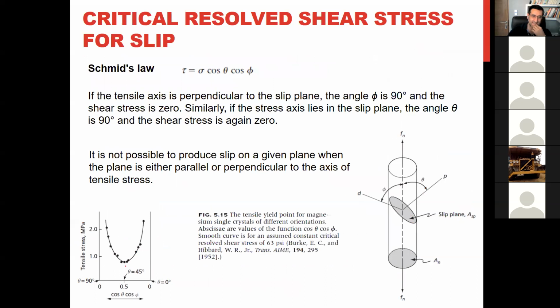And you will see here, if you change these angles or this factor, the minimum will be here when theta is 45. If you change it, you need higher tensile stress to reach the shear stress that you need for a slip. So this is the reason why this angle matters, and why we see these slip planes with this angle on the surface of the sample.